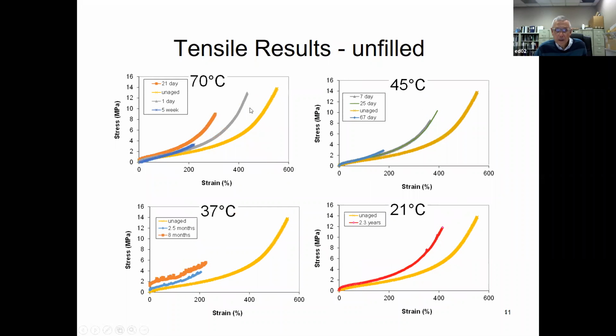And then here are the tensile results for the unfilled compound: 70, 45, 37, 21. Here's the unaged, one day, 5 week, 21 day, and then 45 degrees unaged. And then we have 7 day, 25 day, 67 day. At 37, we have unaged, 2.5 months, 8 months. And then unaged and 2.3 years.